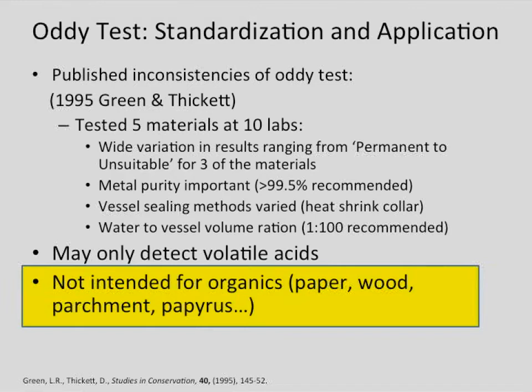We don't use a heat shrink collar, but we go in after our vials have heated up to 60 degrees and we retighten them. And then I monitor those throughout the month to make sure there's still moisture in those vials. If they end up dry at the end, we throw the test away. It's of no use, really.